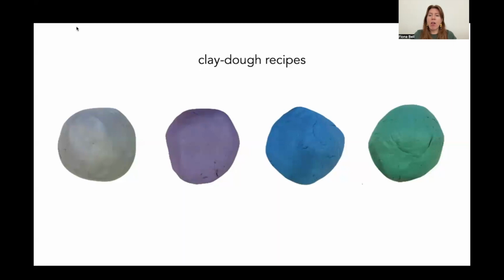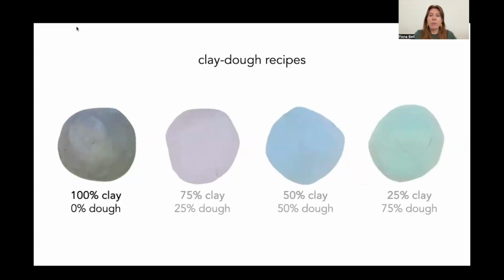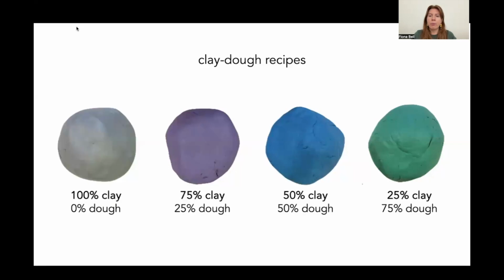In this work, we use the following clay dough recipes. We first use pure clay, meaning that the recipe contains 100% clay and 0% dough. We then use recipes containing 75% clay, 25% dough, 50% clay, 50% dough, and lastly, 25% clay, 75% dough. For clarity, I will refer to each recipe by the amount of clay present within it. We also color code these recipes with food dye to make them easier to track through our design process.